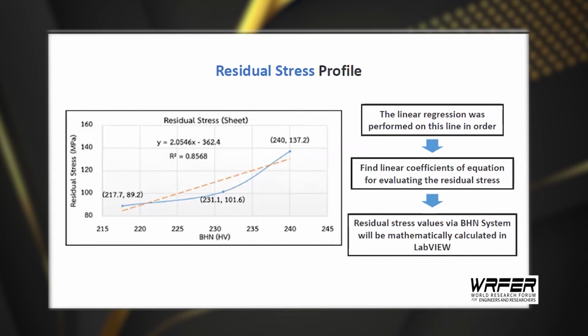This is because the measured signal is the most linear trend feature of the graph. Therefore, the regression equation is applied, which has been converted to residual stress for a sheet workpiece. In the distribution of data in the sheet workpiece, 5% elongation is quite a bit more scattered than the others because the pulling control is quite difficult. Therefore, it affects the measurement accuracy in that range.